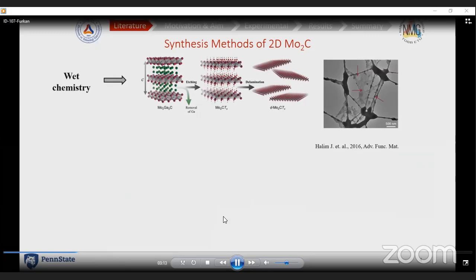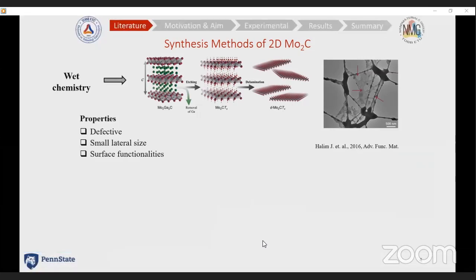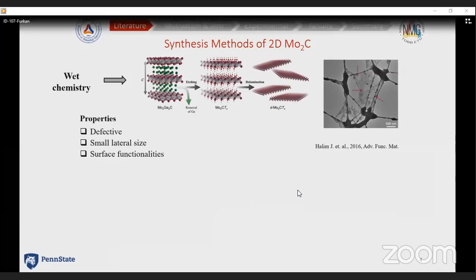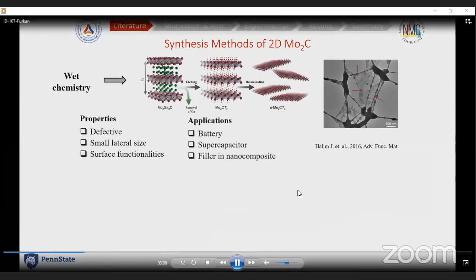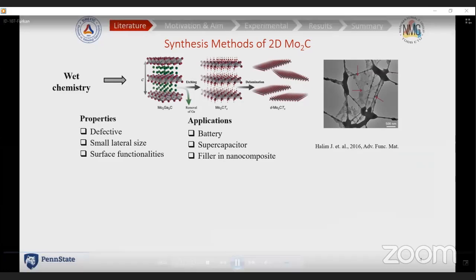However, the bad thing is, these flakes are defective, as you see in the image on the right-hand side, and also they are small in lateral size, and because of the acid treatment, they will have surface functionalities. So because of these three properties, it can be used in battery and supercapacitor applications, and also it can be utilized as a filler in nanocomposites to give better strength.